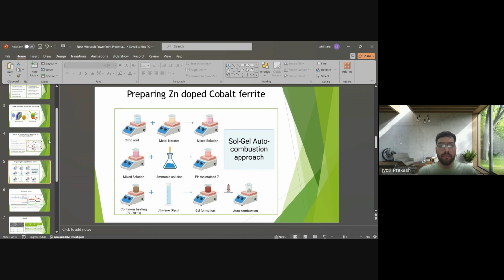So here is the sol gel autocombustion method, which I have utilized for preparing the spinel ferrites. In this method, we use citric acid as a chelating agent and metal nitrates as starting precursors for preparing the solution. After going through the solution phase, we prepare the gel phase. The gel phase is prepared using ethylene glycol, but before that, we have to maintain the pH at 7 using ammonia solution. After adding the ethylene glycol, we get the gel formation, which is then heated to start the autocombustion reaction. After that, we get our final product, which is ground and calcinated to attain phase purity.